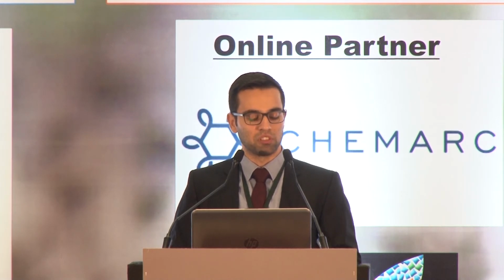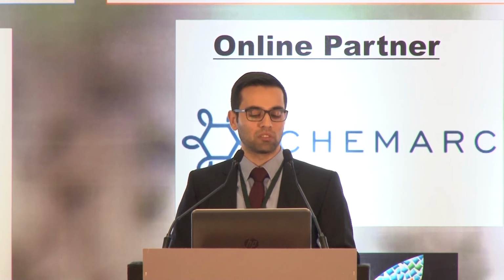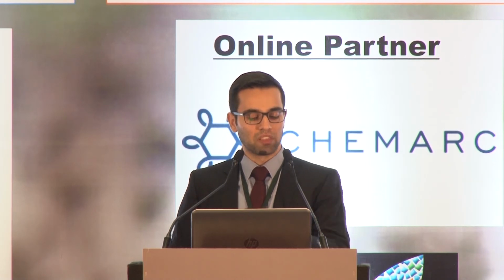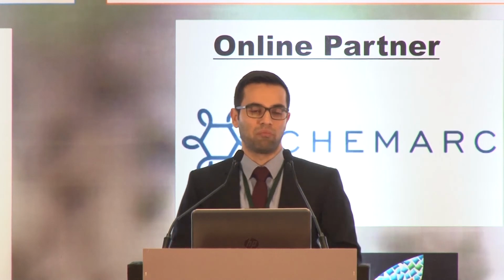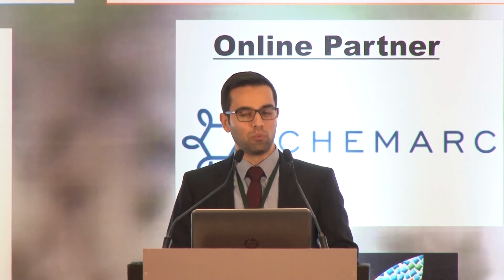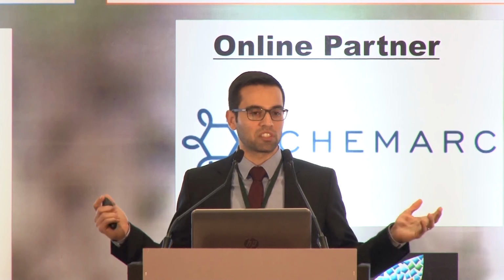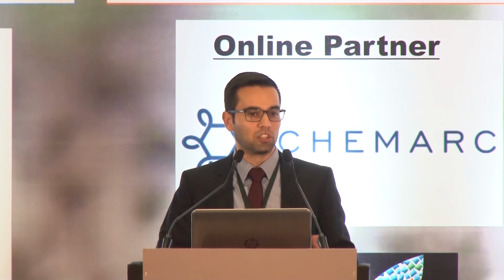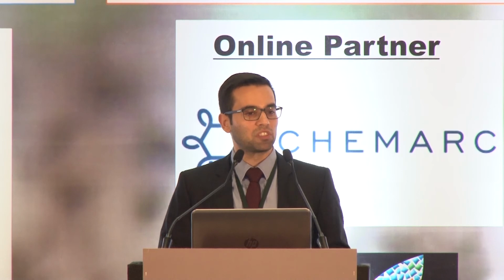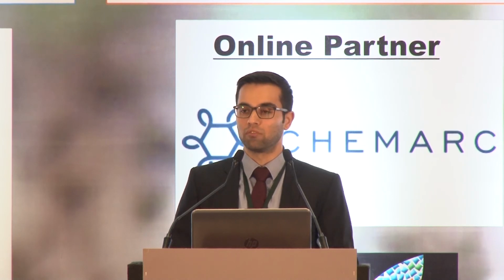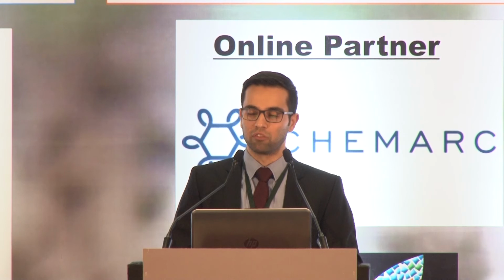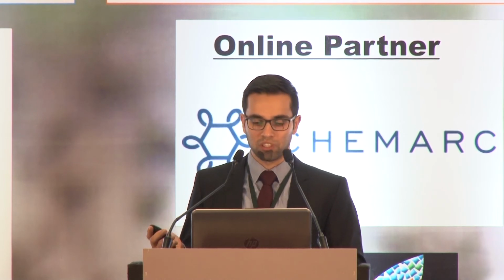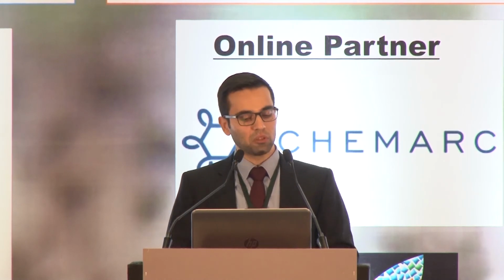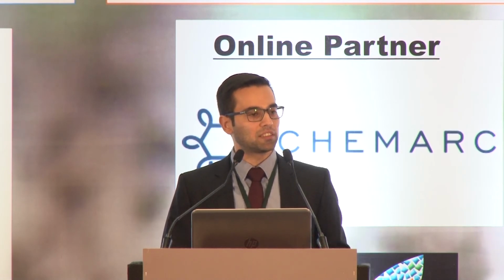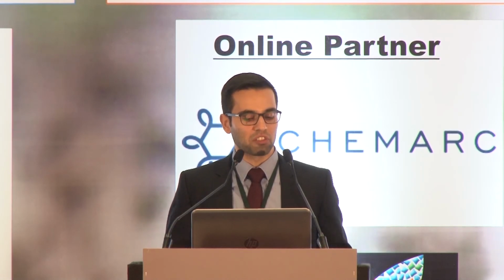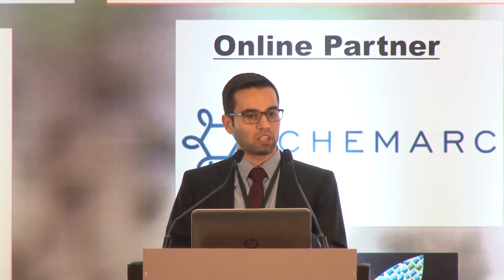We have the 2004 product, also for the same polymeric applications, but this you can use also for polycarbonate. We have many LED applications in polycarbonate, where people think, okay, we can't use this, literature says so, and everyone says you can't use a slightly basic filler, but when you do the right chemistry, we were able to do that. So also for polycarbonate, we can apply. We have a few running projects in Germany with polycarbonate. Now the 3000, this is a very, very low viscosity grade. Of course, packing density, surface treatment, right morphology. And these products are ready to use.